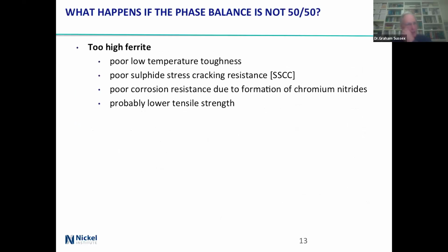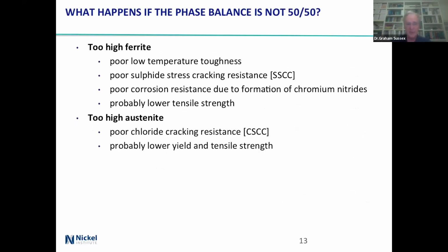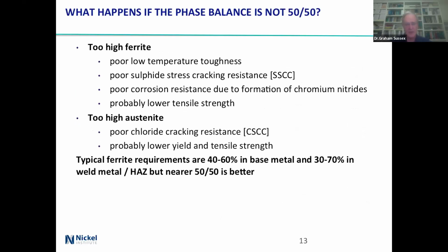If you get too high ferrite, though, you get poor low temperature toughness, pretty awful stress corrosion cracking from sulfides, poor corrosion resistance because of chromium nitrides forming, and probably lower tensiles. You get too high austenite, hey, chloride stress corrosion cracking, here we come, and you'll get lower yield and tensile strength. Typically, you aim for ferrite of 40 to 60 in the base metal and 30 to 70 in the weld and heat affected zone, but the closer you can get to 50-50, the better.